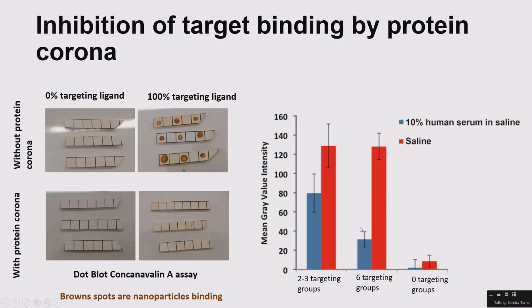And what's interesting as well is we tested using 6 targeting ligands per polymer on the particles versus 2 to 3. More doesn't necessarily mean better, because it depends on the configuration of these ligands on the polymer. In fact, the 2 to 3 targeting groups worked better, probably because their configuration was less influenced by the protein corona.